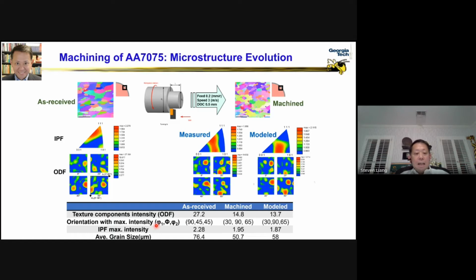We can see that, for example, the inverse pole figure has a maximum intensity before cut of 2.28, and it dropped to below 1.9 something. Very well predicted with our model in comparison to the actual machined parts. Average grain size drops dramatically by machining, as predicted and very well compared to experimental measurement. The hardness of the part increased significantly by machining, very well predicted and very well compared to experimental data.